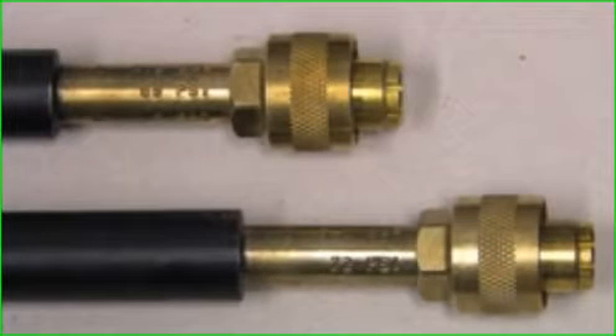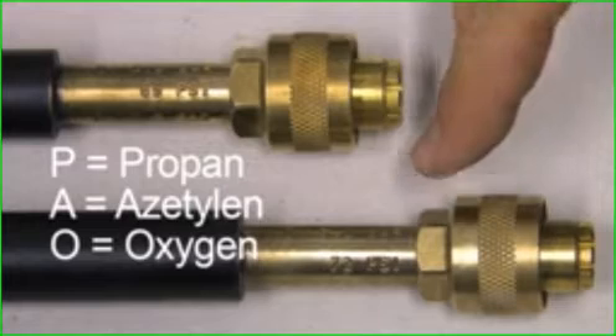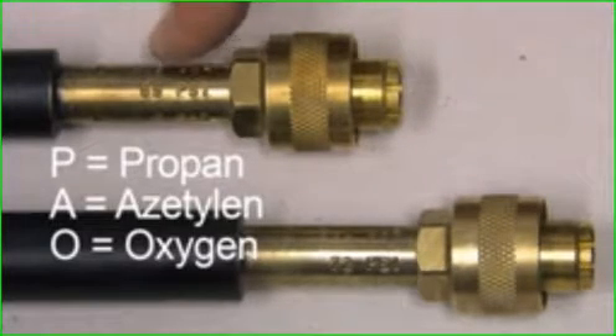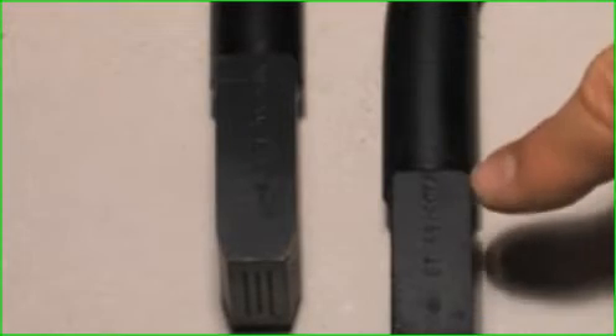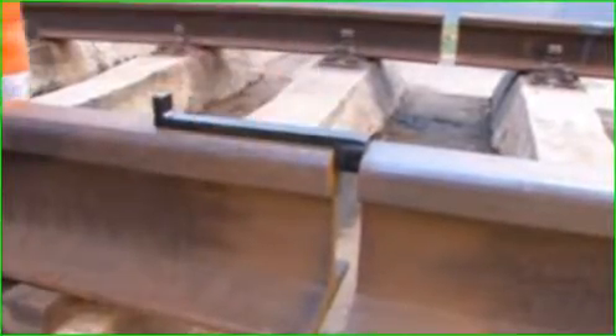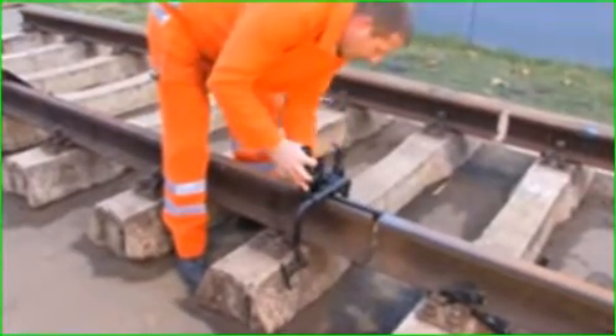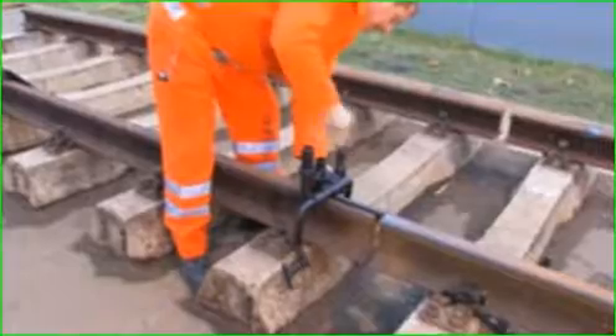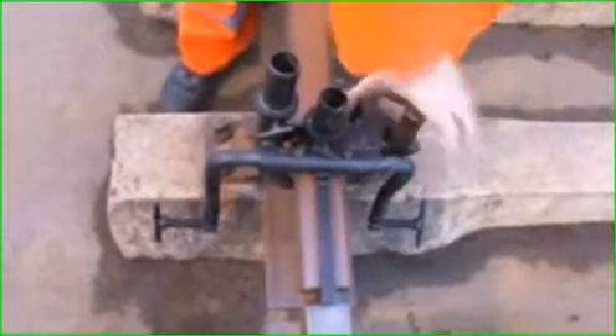The correct preheating torch is to be selected. On each torch is permanently marked by which gases and which working pressures it shall work. Stamped number at torch head shows the torch type. In Code of Practice, you can see which torch type is to be used for which welding process. The clamping device is to be fastened at the rail head without canting at the distance to the welding gap specified by the setting gauge.